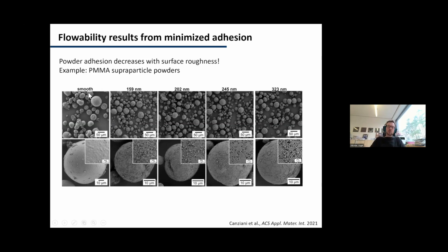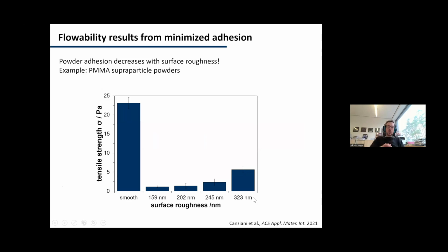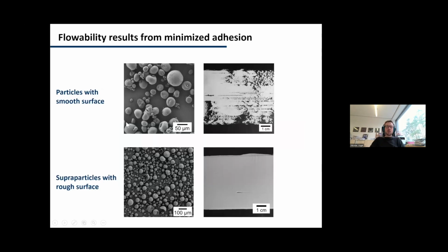If we compare smooth particles to rough supraparticles with different primary particle sizes, then you see we can make powders that essentially look the same, except the surface roughness is a bit different. And when we now look at how these powders flow, which we assess via a tensile strength, then you see the introduction of surface roughness really, really drastically changes the tensile strength or the cohesion within the powder. And as a result, if we compare the flowability by simply doctor blading a powder layer, you see that the supraparticles flow very well and form dense layers, while the same particles with a smooth surface do not flow so well and then create problems in your powder bed. And that will translate, of course, to the final printed product.